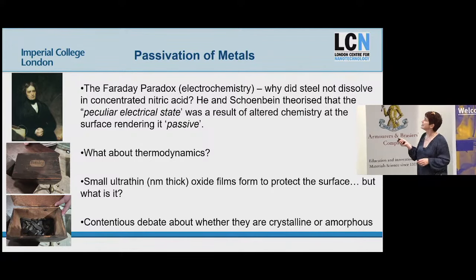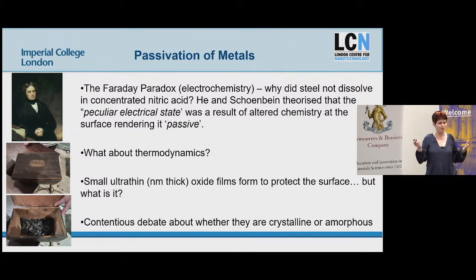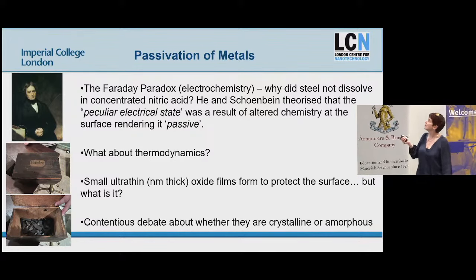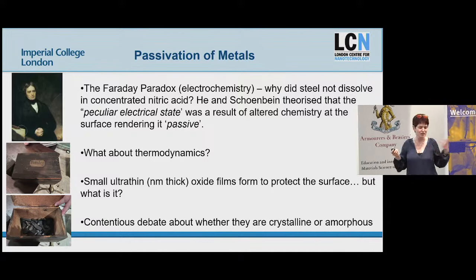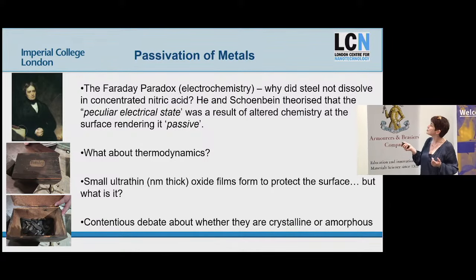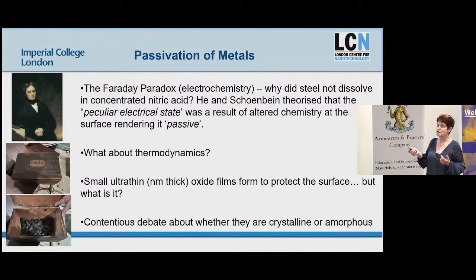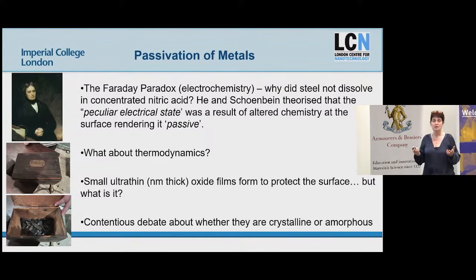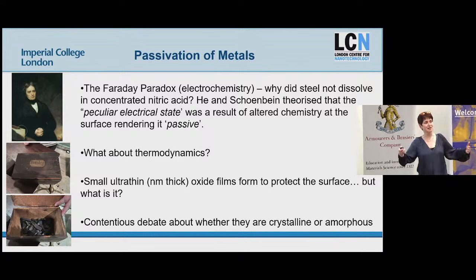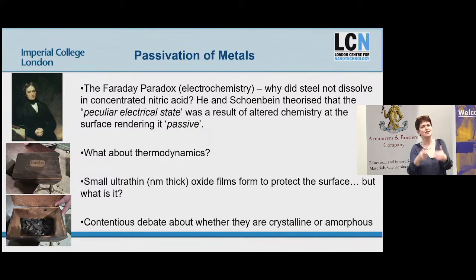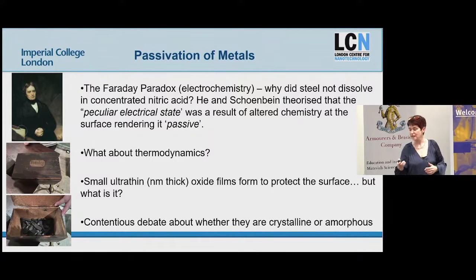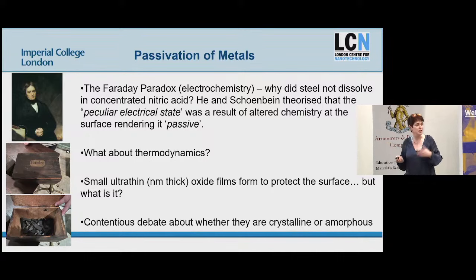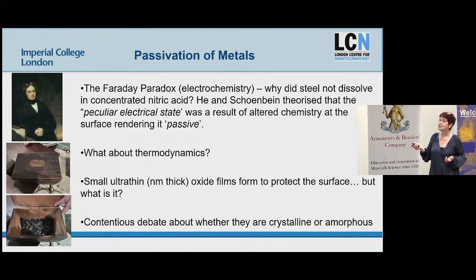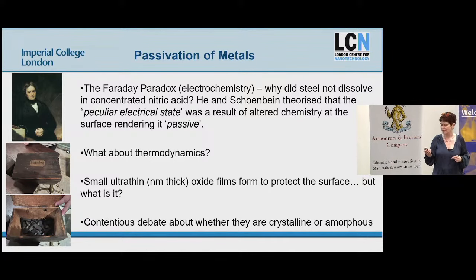And actually, Faraday, as in most things that we think about in electrochemistry, Faraday had already thought about some of this, and he and Schoenbein wrote letters to each other about some peculiar experiments he was doing, and he was actually the first person to describe this altered state of a surface, which he called passive. So what that means is that yes, the thermodynamics are a huge driving force, but the kinetics are so slow that actually you're going to take thousands of years to revert back to that native state. And he postulated that something on the surface was causing this. The surface state was altered. The surface was stopping the thermodynamics from winning in that scenario.